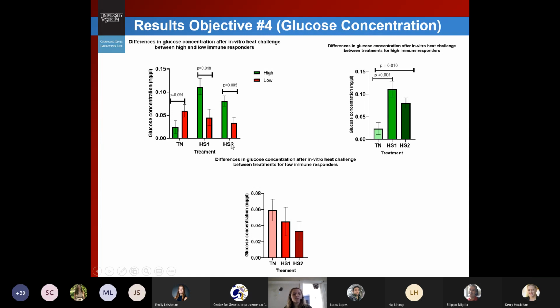Versus when we get out to after 2 heat stress treatments, we then see a switch, with our high immune responders producing more glucose compared to our lows, possibly indicating that now the highs are switching to using more of that glycolysis pathway versus our low immune responders. And then when we look within phenotype across the treatments, we do see a significant increase in glucose concentration compared to thermoneutral for the highs after our 2 heat stress treatments, versus the lows.